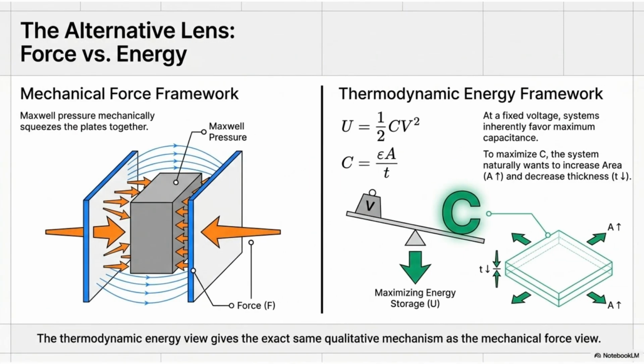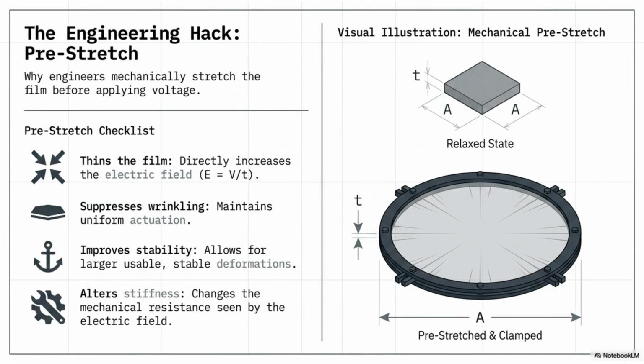Two lenses explain DEA function: the mechanical force framework, based on Maxwell pressure, and the thermodynamic energy framework, based on maximizing energy storage by increasing capacitance. Both views describe the same qualitative mechanism. Mechanical pre-stretch is an engineering hack used to thin the film, increase the electric field, suppress wrinkling, improve stability, and alter stiffness. This allows for larger, stable deformations.